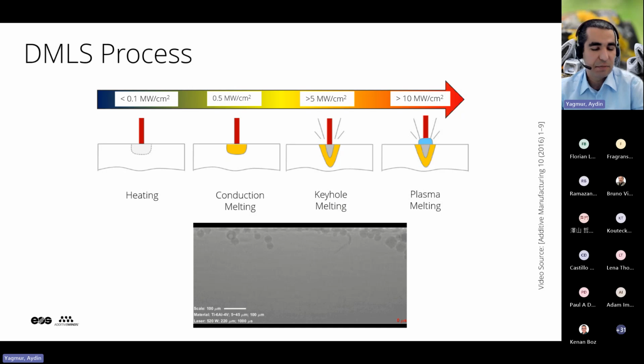So how do laser and material, or metals, interact? We have a good first approximation using power density and the corresponding behavior of the metal. If the power density is less than 0.1 megawatt per square centimeter, this is simply heating of the material. If we increase the power density to 0.5 megawatt per square centimeter, we observe conduction melting. If we go on increasing the power density, we have so-called keyhole melting, which is the heart of our technology.